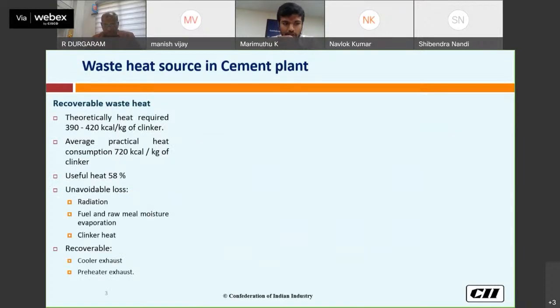First, coming to the waste heat source in the cement plant, as the point already put up by Manish, I'm going to add some more points. In the cement unit, for production of 1 kg clinker, the theoretical heat required is 390 to 420. But actually, what we are achieving is around 720 kilocalorie per kg of clinker. In some units it's around 680, in some units we are getting 750 also. On average, we are getting around 720 kilocalorie per kg. In this 720 kilocalorie, we are utilizing only 58% for clinker production. The remaining 42% we are wasting.